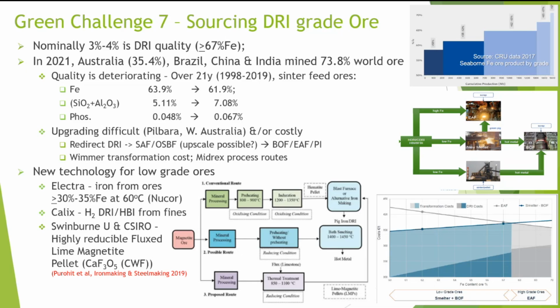But currently the thought process is, and not just for Pilbara, but with the lower grade, weaker ores, that we redirect the DRI into a melter, so a submerged arc furnace, basically an SAF, and then put it to a BOF or an EAF as hot metal or as pig iron.